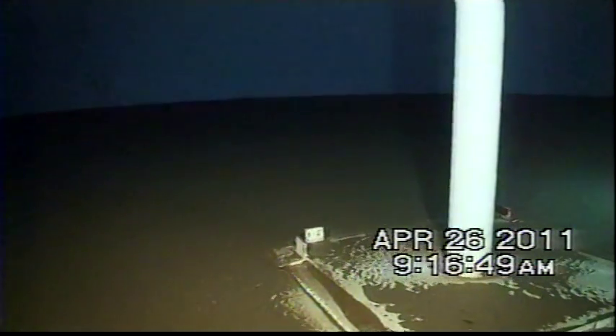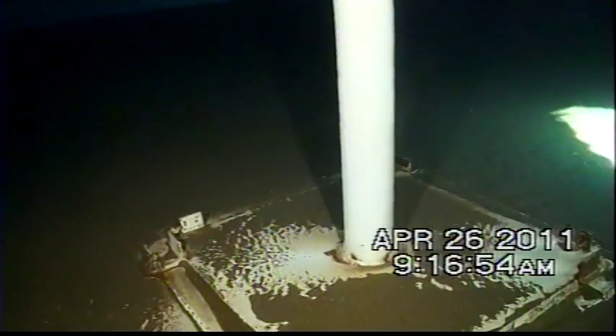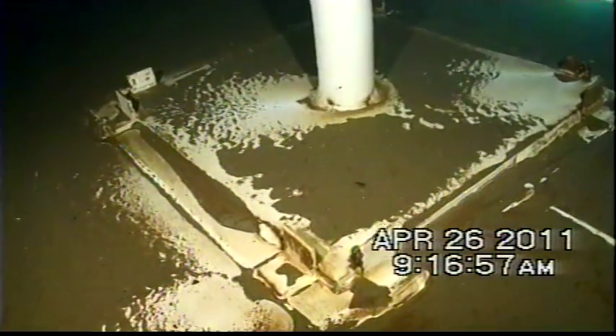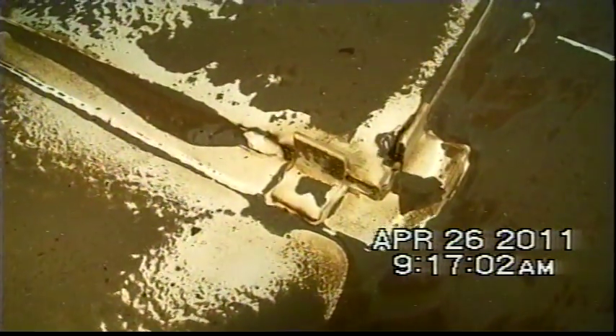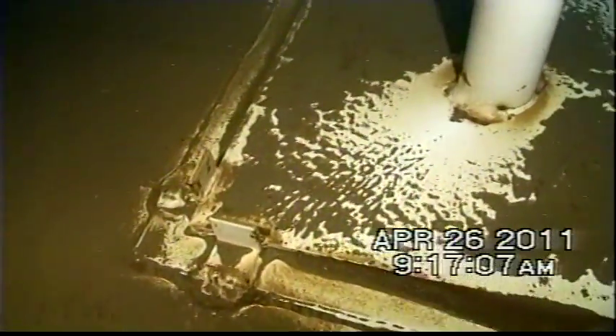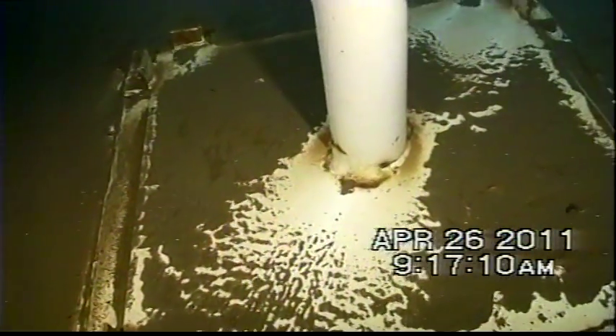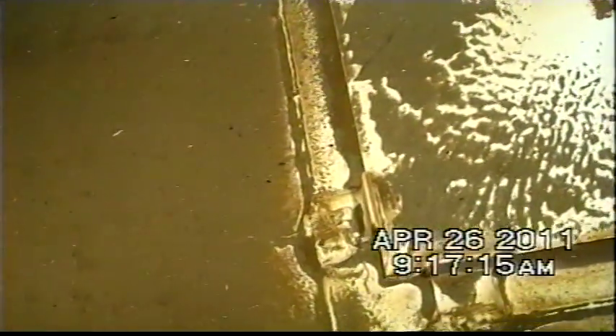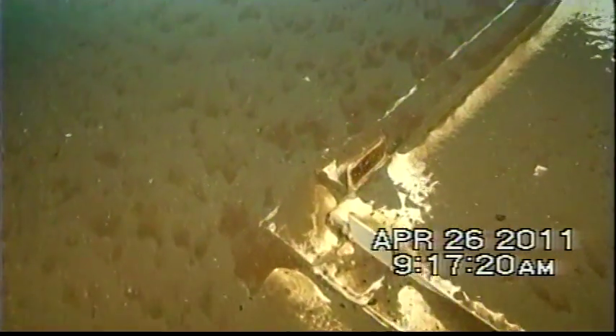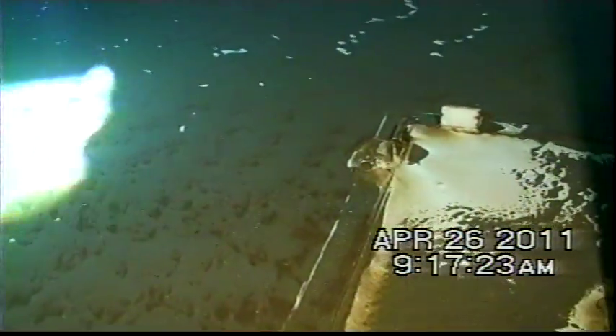The majority of the epoxy coating on the base plate is in good condition. Coating defects have resulted in pinhole type corrosion in approximately 12 locations on the base plate. The bulk of the epoxy coating on the center pole below the waterline is also in good condition. Coating defects have resulted in corrosion in approximately 12 locations on the center pole below the waterline.